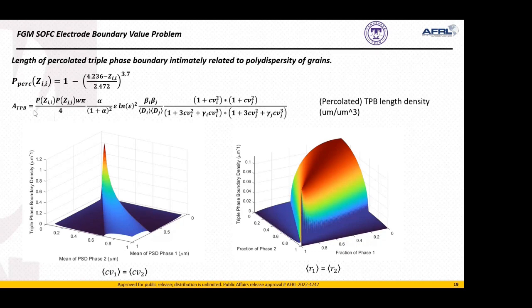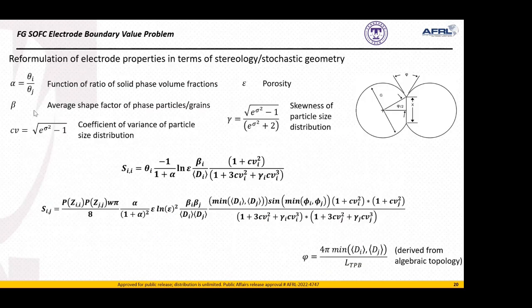As well, on the right-hand side, this map is perhaps interesting to look at if we had an electrode or a microstructure composed of multiple phases, 3 or 4 phases. For a biphase material, obviously the only compositions that are possible are just going to be a plane that is cut across from 100% phase 1 to 100% phase 2. So we would take a cross section of this mapping here. But this shows how tuning the initial inks and powders can also increase our electrochemical activity.